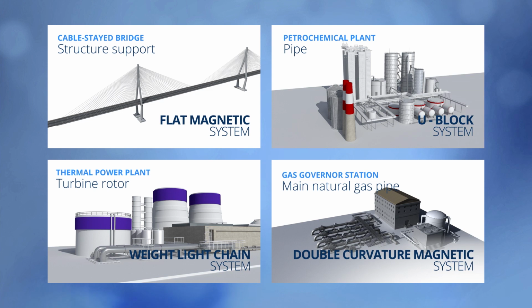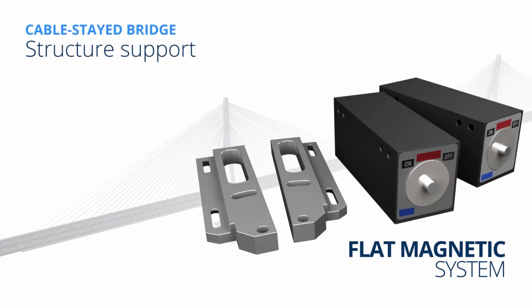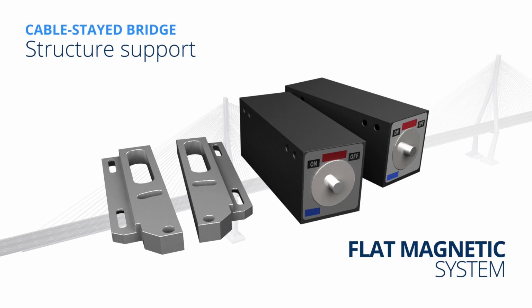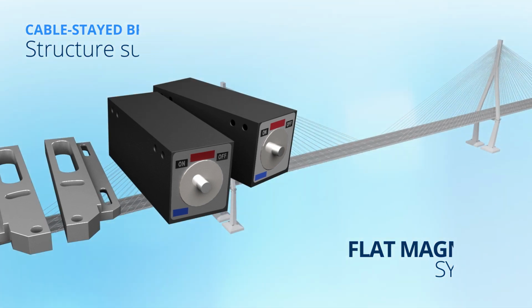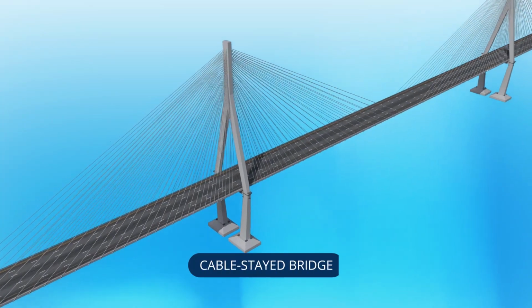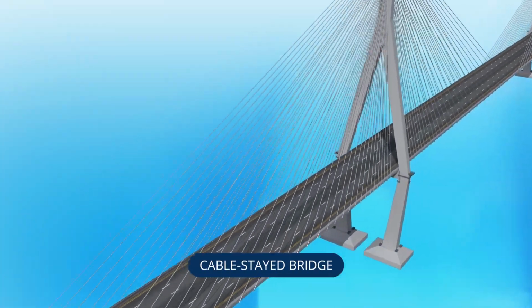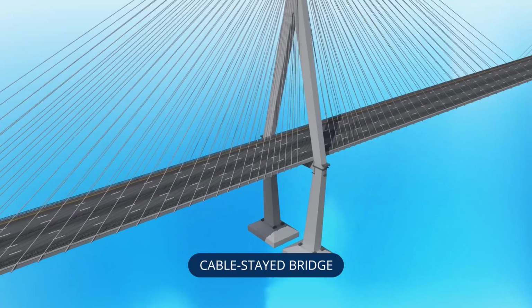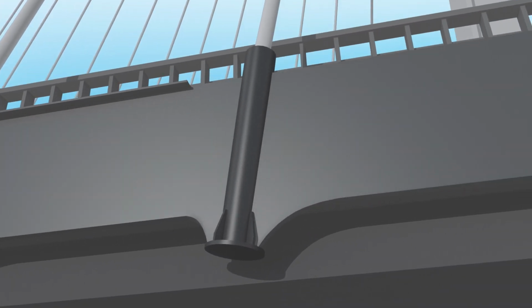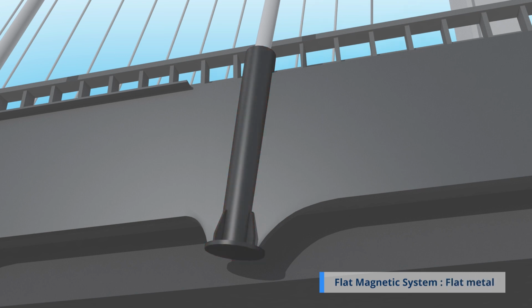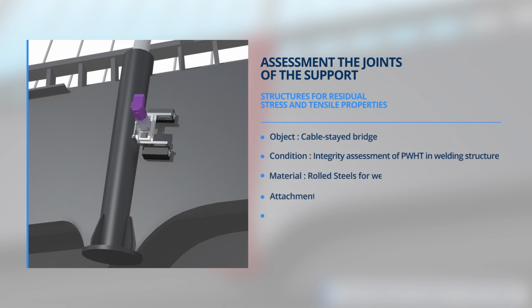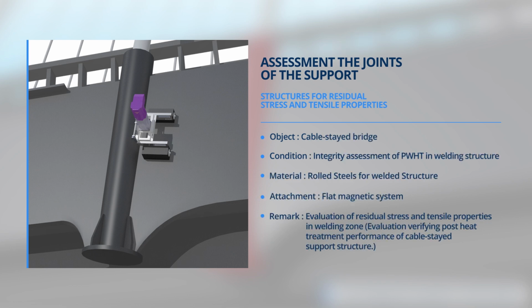The case to be introduced first is a cable-stayed bridge. The attachment to be used is the flat magnet system. It's the attachment using a flat magnet system, which is optimal for flat metallic shapes or structures. It's necessary to first check the test object and position. The object for the test is a welded support structure of a cable-stayed bridge, and the test is intended to evaluate the integrity of the structure welded and heat-treated. Besides, bridge deck and metallic plate are also applicable.